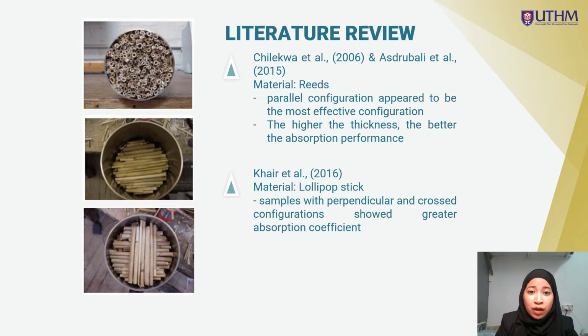Results showed that the peak of the SAC shifted towards lower frequency with increasing thickness in the vertical tested samples. He also concluded that the higher the thickness, the better the absorption performance. Lastly, in 2016 a study was conducted on the sound absorption performance of a hollow tube structure made up of lollipop sticks. The result demonstrated that samples with perpendicular and cross configurations showed greater absorption performance. In addition, incorporating an air gap in the parallel tested samples moved the peak to a lower frequency. However, no effect was found by introducing the air gap in the perpendicular and cross tested samples.